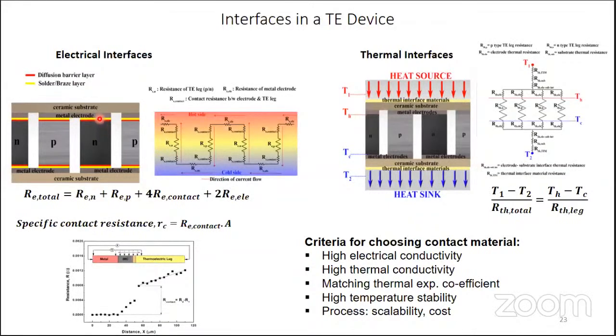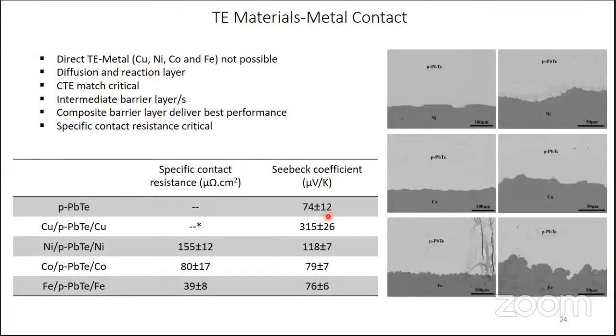So this is very, very critical. That is the specific contact resistance. Like this, the resistance to heat flow also should be low. And this is our contacting lead telluride, whatever we made. Nickel as an electrode, we use it. Here you can see that we tried nickel, cobalt, and iron, all these things.